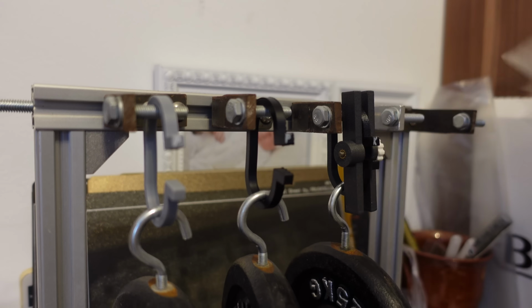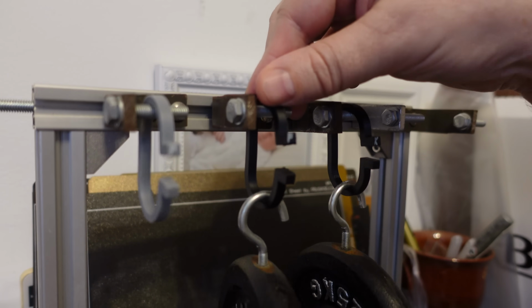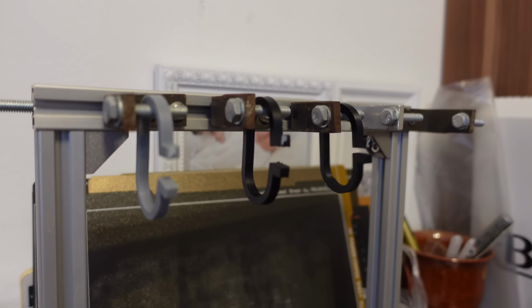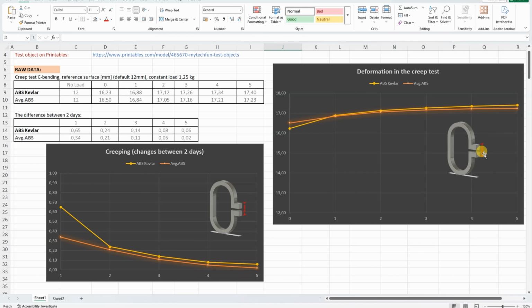17:40. Removing the load. On this graph we can see the distance between two reference surfaces, and we can see less initial deformation on ABS Kevlar. But after day 1 they became almost equal, and from here their deformation is very similar, but the difference between 2 days is the creeping that's presented on the second graph, and here we can see bigger creeping on day 1, but after this the creeping is very similar. But from fiber reinforced material I was expecting better properties.